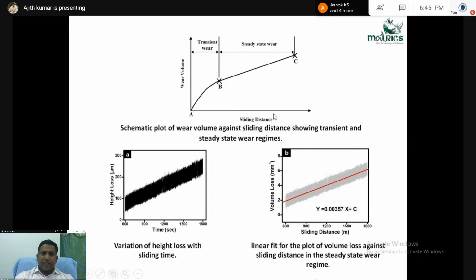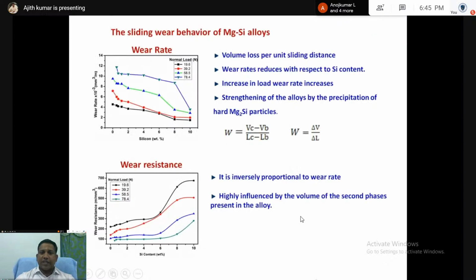You see, in every wear graph of sliding distance and wear volume, initially A to B is a transition wear, and after that B to C is a steady state wear. Always we take steady state wear for further analysis. In the steady state wear region data, we take height loss versus time. From the height loss plus time graph, we can get the slope value of wear rate. So wear rate is the volume loss per sliding distance.